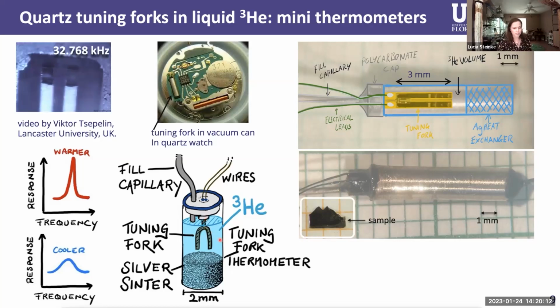And that allows me to make this bath really small and then make completely self-contained thermometers with helium-3 inside that are of similar size to the samples I want to measure. So now I can use them as probes for the samples. And the viscosity of the helium-3 inside is strongly temperature dependent. It gets more viscous as it gets colder.